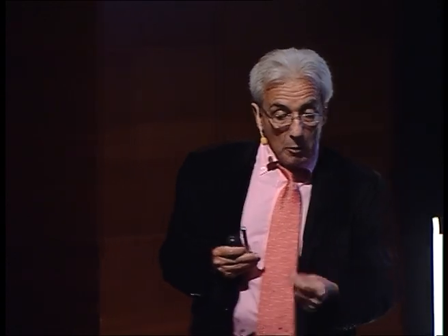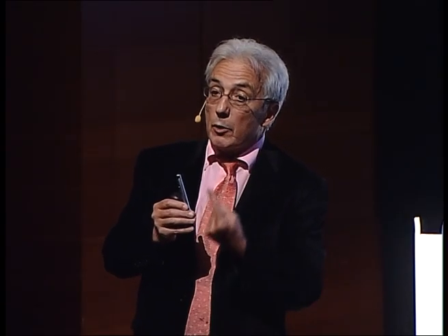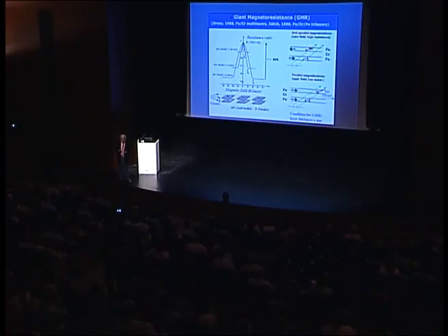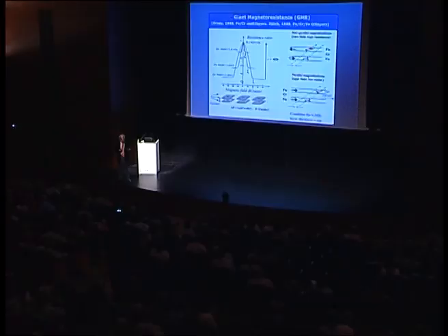The detection works like this: when the multilayer sees one of these small fields, this field aligns all the magnetization of all the layers, and the resistivity drops, and you can detect the increase of electrical current. And so the sensitivity of the GMR allows detecting smaller fields, smaller bits, and increasing the density, the number of bits you can put on the same disk. For example, this density has been increased by almost, I don't know, the last number was 600 times from the generation before.